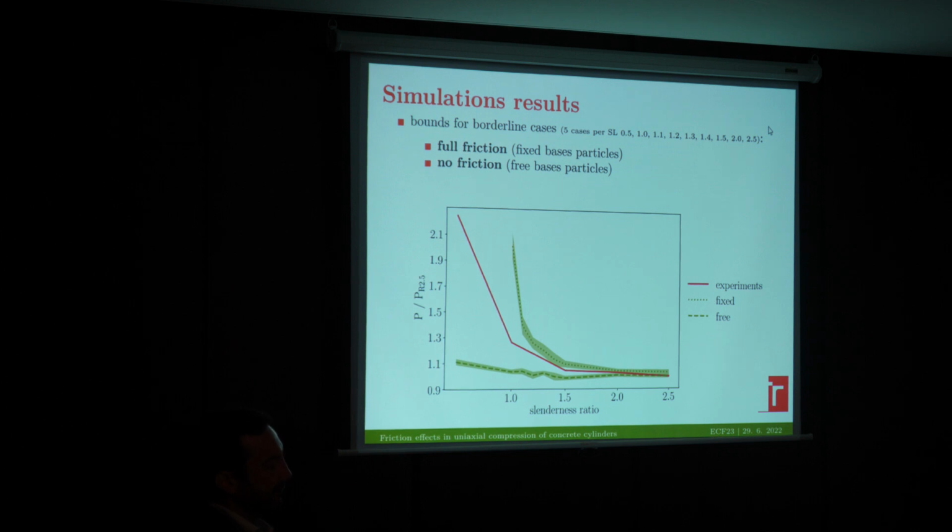I work a lot on this geometry and size effects in particular, considering of course the friction action, but I use some device to avoid friction. Yeah, that's also possible, to use Teflon. I use tubes, Teflon, with oil in between. It was impressive because the problem was that the specimen would move around because there was no friction at all. It's difficult to center. No, it was simple. The problem was to completely avoid the friction. Strange. Thank you very much.